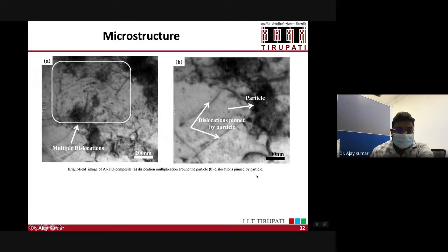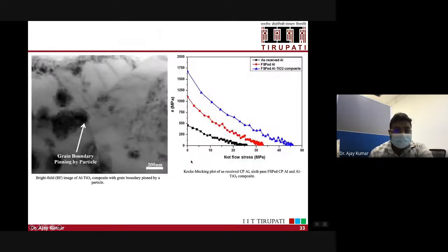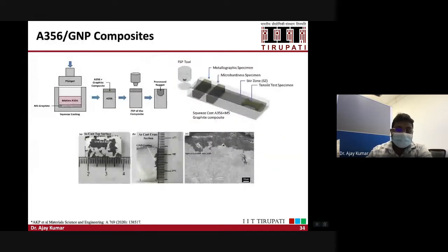Then this is an example of dislocation multiplication and dislocations pinned by the titania particles in the aluminum matrix. And then you can see these are the grain boundaries, and these grain boundaries are pinned by the titania particles. These are the high magnification images where you will clearly see the strengthening mechanisms operating, which we discussed in the previous slide.